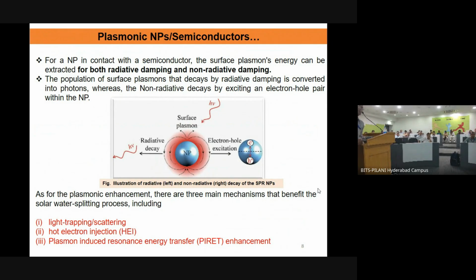The first part of it is the excitation. Due to the surface plasmon resonance for the noble metallic particles, the light absorption cross-section increases, so you have more light that is absorbed, as a result of which the excited particle now has two options. Through a radiative decay, it can release its energy, or it can create additional electron hole combinations. So whatever combination you can think of, the plasmonic enhancement can be utilized either by increasing the light trapping or the cross section. That depends on small versus big particle.